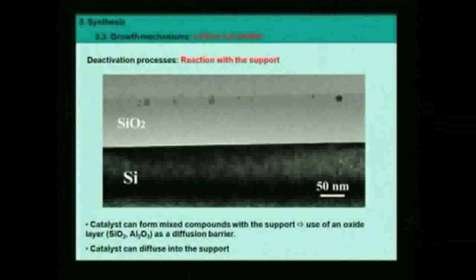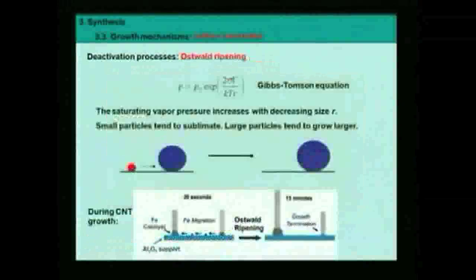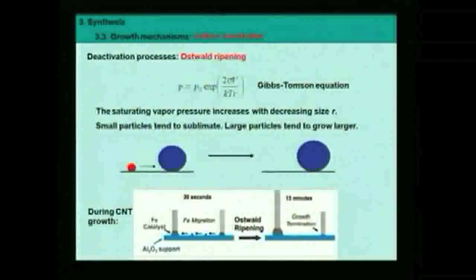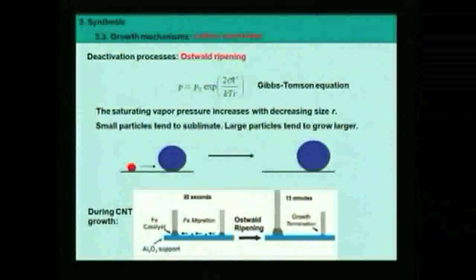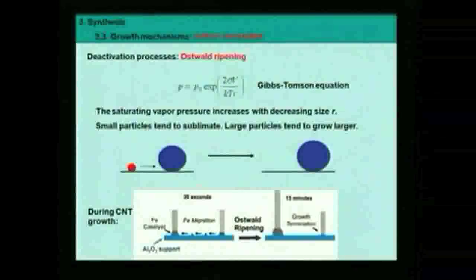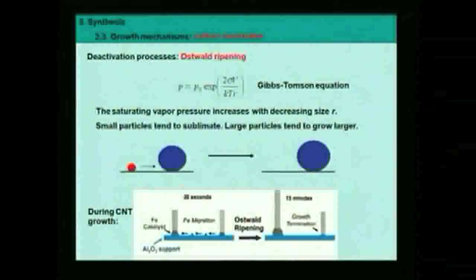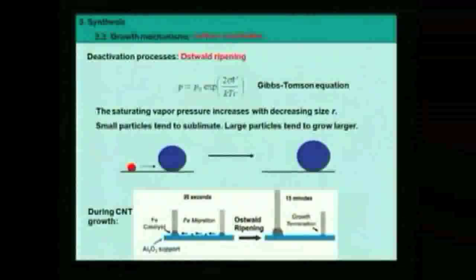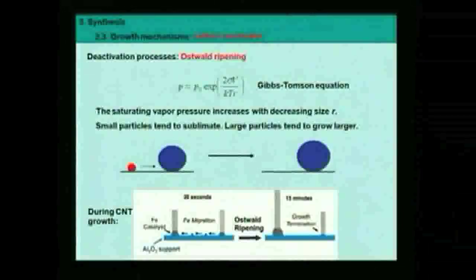But you can also have other problems like diffusion in the bulk of the surface. So this has also to be taken into account. Okay, Ostwald ripening, I'll not go into details of that, but it's a consequence of the Gibbs-Thomson equation that you see here. The small particles have a higher saturating vapor pressure than large ones. As a consequence, they sublimate, they disappear to the benefit of the large particles. This is the phenomenon called Ostwald ripening. It can occur during the growth, and then the small particles disappear and the remaining tube cannot grow anymore because there is no more catalyst there.